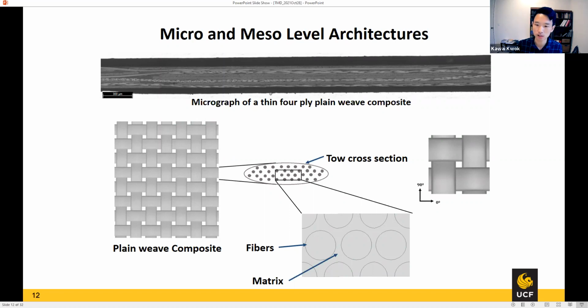The first architecture is more on the micro scale, and there's just the tow cross section. So there's about 10 fibers, right? 10 carbon fibers. Each one is about 5 microns to 7 microns for the thin ply. So you get basically a unidirectional type of microstructure, a unidirectional composite.